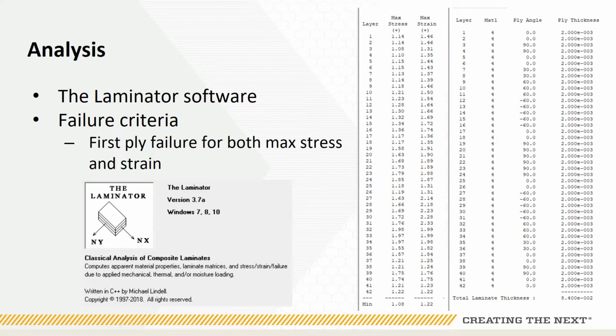For our analysis, we used the Laminator software shown in the bottom left figure. By inputting our ply orientation and given loads, the software calculated the stresses and strains in the midplane of each lamina. For our failure criteria, we used the first ply failure method for both maximum stress and strain. This meant that any time a single lamina had a stress or strain over the failure value, the entire laminate was considered to have failed. This is a very conservative method, but it automatically designs in an extra safety factor, which is beneficial for aerospace use. An example of this analysis is shown on the right.